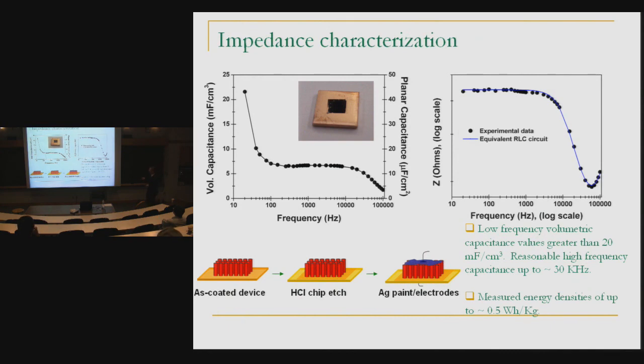So once I did this, the question is, okay, what is the capacitance? One of the ways that you can extract the capacitance from these structures is to simply do a frequency-dependent measurement of the complex impedance and fit this to some equivalent circuit model. You can do this via a program such as PSPICE, where you can extract from that, given a good equivalent RLC circuit model in this case. Of course, this looks like a bandpass filter. You can extract the capacitance. The other thing is you can measure this directly from an impedance meter or an LCR meter and extract out the capacitance of this.